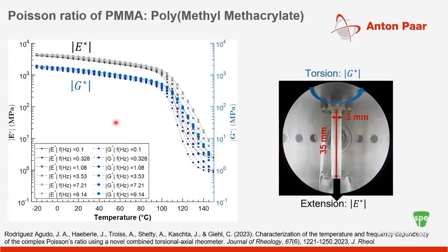Hopefully I'll show you more data here. Based on that G and E measurement using the combined axial torsional mode, you can now study this as a function of temperature within a single test protocol. And this was not really possible before. You see the evolution of both moduli here, below the glass transition and above the glass transition.